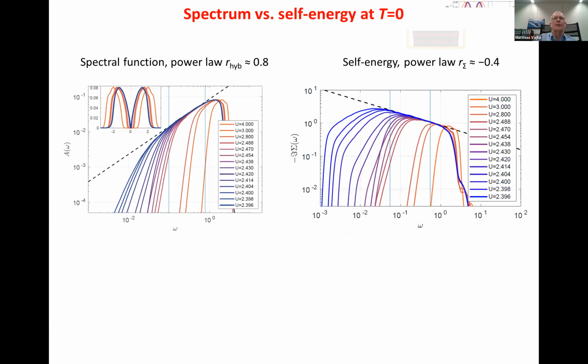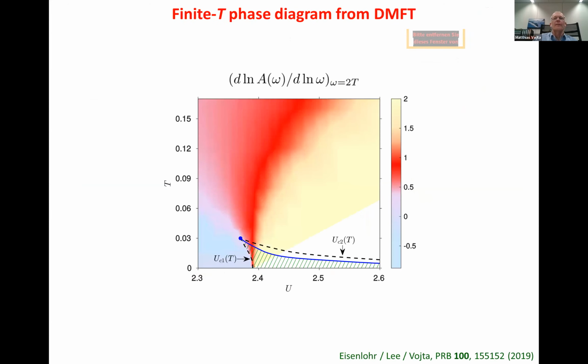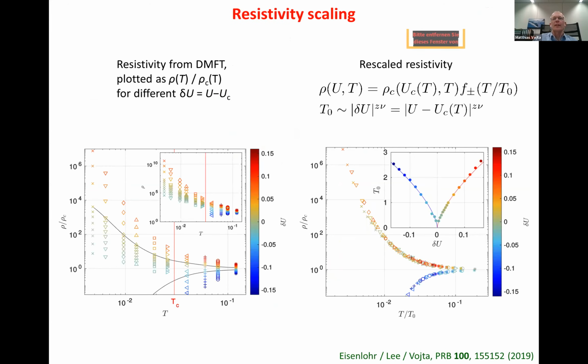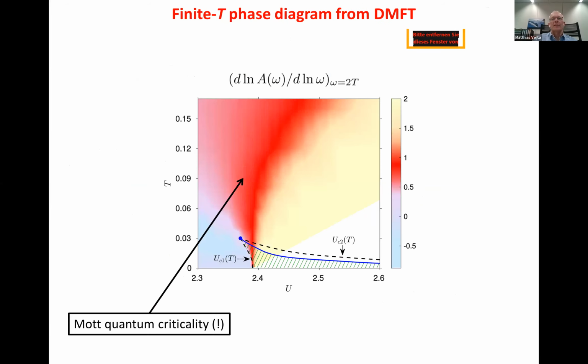What I showed to you is somewhat different. I showed to you this plot, which was a scaling plot. And actually this branch of the curve, which goes very deep into the insulating state, actually goes to temperatures below TC. What we decided is to follow the metastable solution. And this plot here as well is generated by focusing on the metastable solution in this regime. In other words, if you focus on the thermodynamically stable thing, then everything I told you is cut off at this big blue line where the first order transition is.